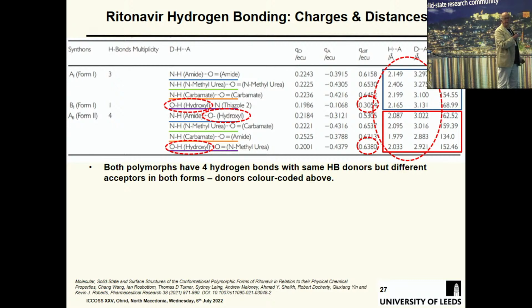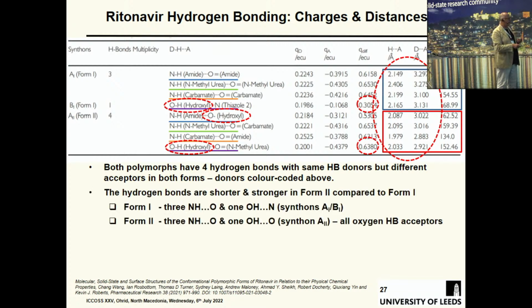So this is another thing you might have noticed in development. You had this crystal structure when you developed the material. You might have thought to yourself, OH...N, isn't there a better acceptor than a nitrogen? Maybe. And later you'll see that same one down here has found a better pair. So you basically got an OH...N and an OH...O, and the OH...O is always likely to be a stronger interaction. And the other thing you see is the hydrogen bond distances are much longer in Form 1 than in Form 2. So the hydrogen bonds are shorter and stronger in Form 2.